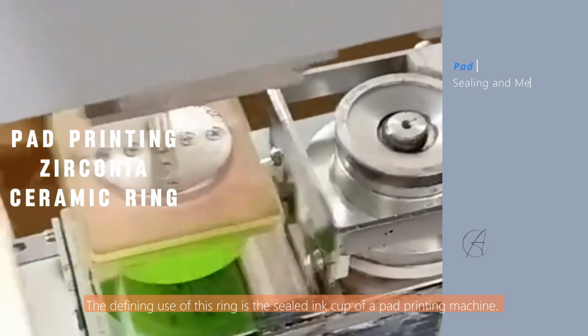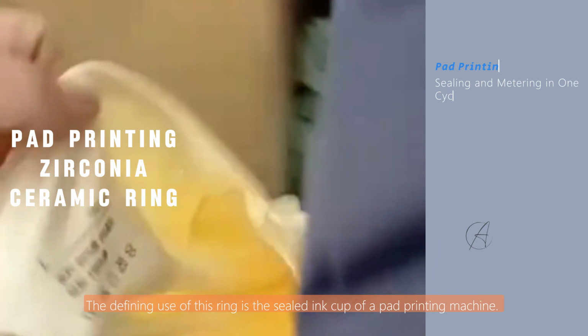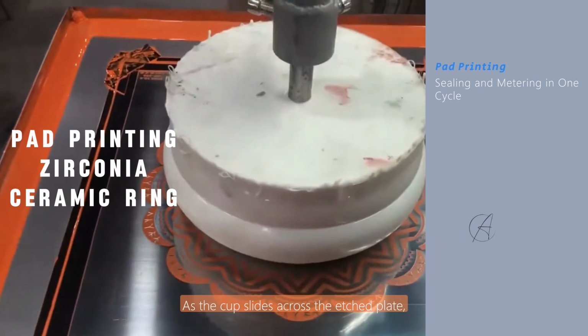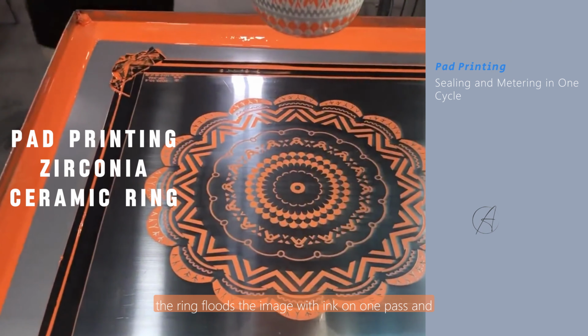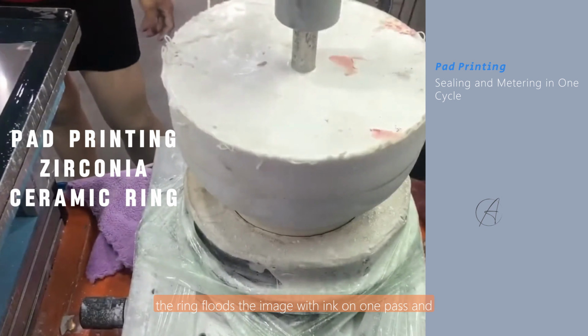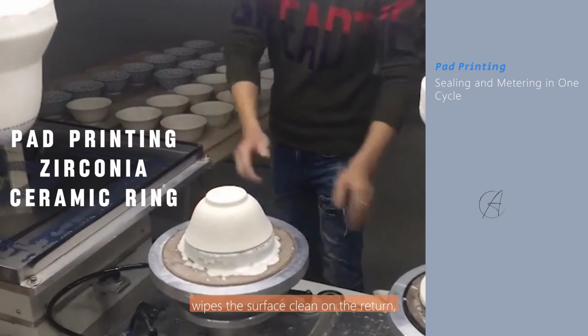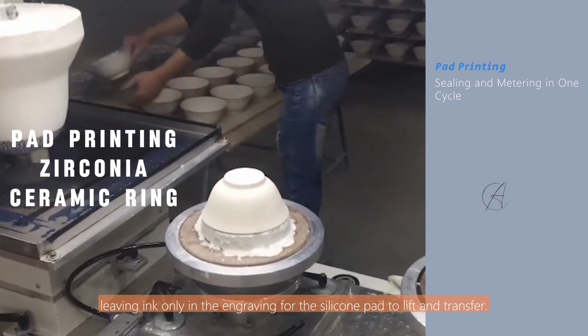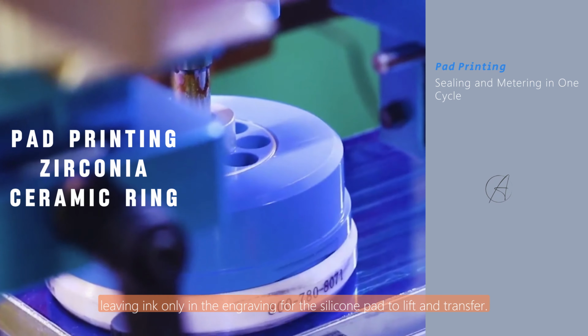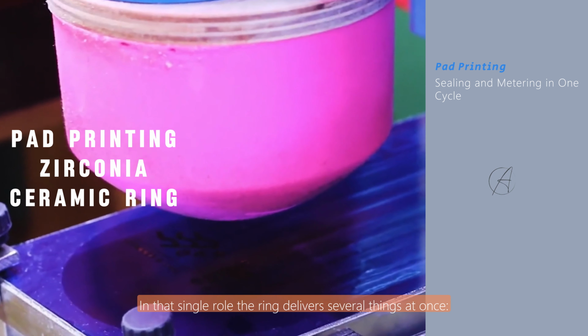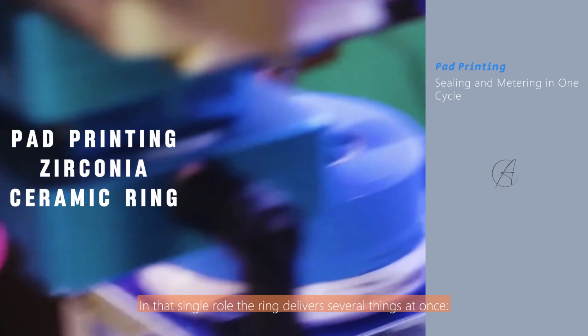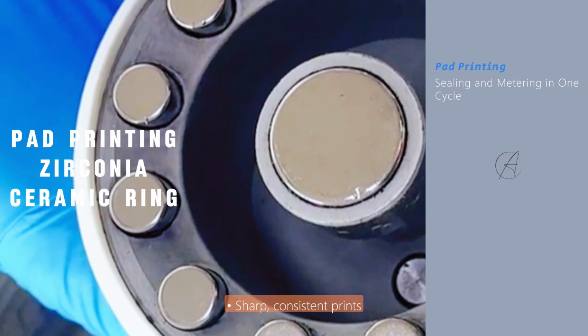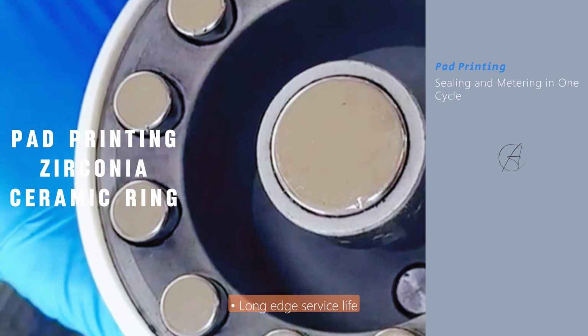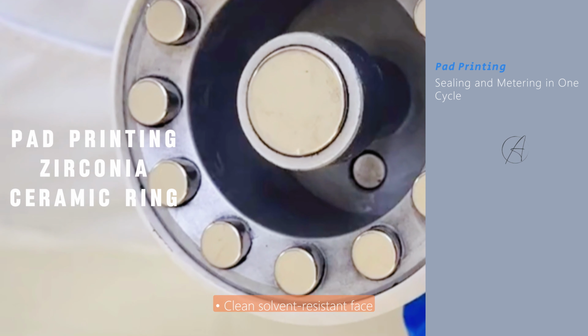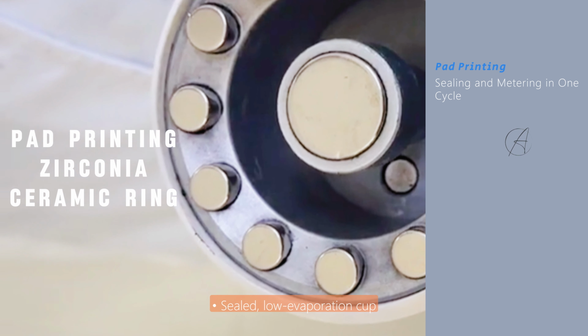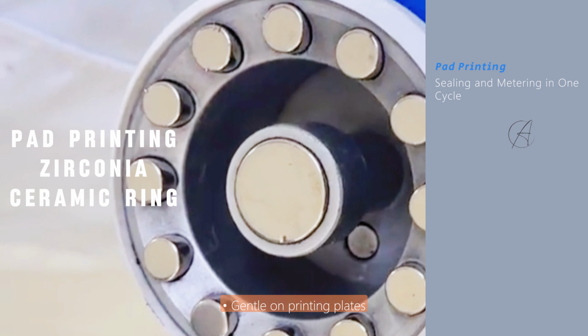The defining use of this ring is the sealed ink cup of a pad printing machine. As the cup slides across the etched plate, the ring floods the image with ink on one pass and wipes the surface clean on the return, leaving ink only in the engraving for the silicone pad to lift and transfer. In that single role, the ring delivers several things at once: sharp, consistent prints, long edge service life, a clean solvent-resistant face, a sealed, low evaporation cup, and gentle treatment of printing plates.